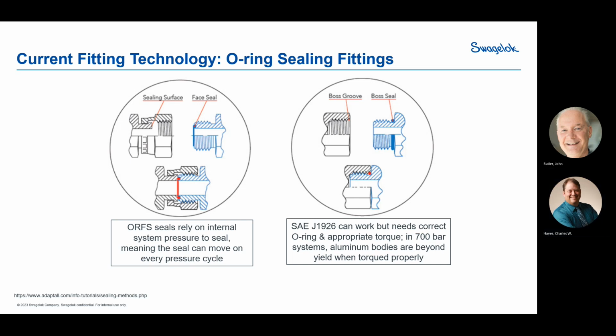But here are the problems. People don't usually torque these and hit the torque specification. They take it to, that's tight enough. You know, the little grunt on the wrench when you pull it up, that seems good. And if you don't put enough load in, especially in higher pressure hydraulics, the pressure working on the face of that fitting will actually cause it to back out and overcome the stress of the preload. So that's a problem. The other place it becomes a problem is if you're going into aluminum components.